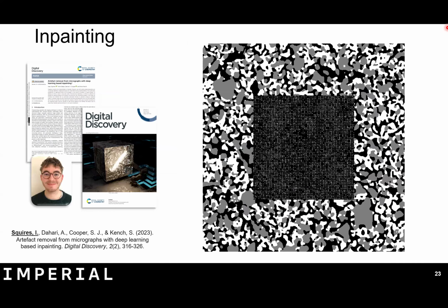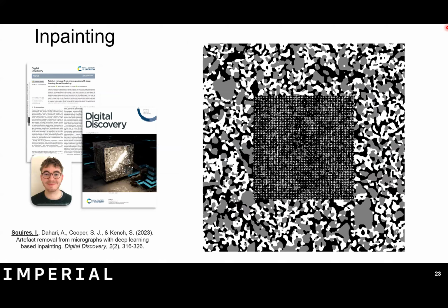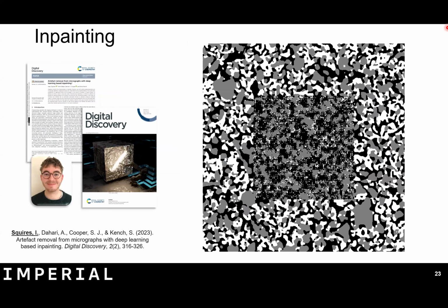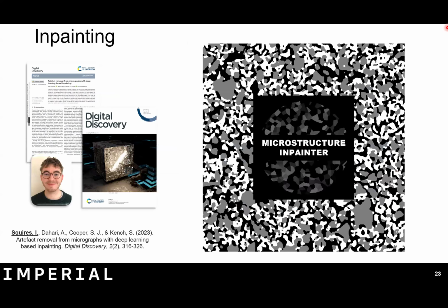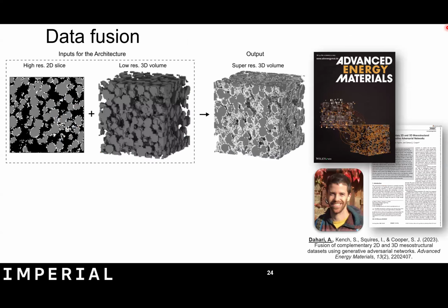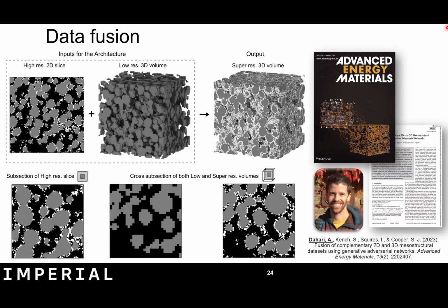You can use very similar technology to do things like in-painting. So if there are missing or damaged regions in your data, you can fill those in. And you can also do things like data fusion, so combining multiple modes of imaging. So combining high resolution SEM imaging with low resolution XCT imaging, a wide field of view, but high resolution combined image. And what you can see on the bottom row is just little patches from the top row, is that the output is the same structure as the low res, but the same statistics as the high res.